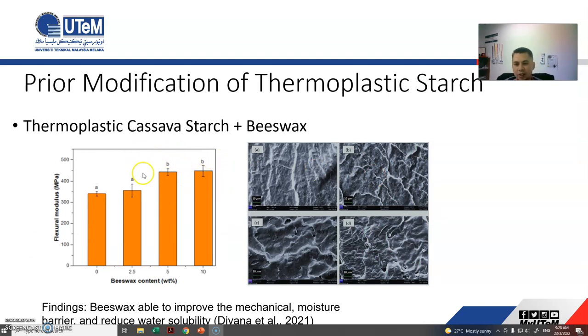In this study, previously we modified the thermoplastic cassava starch by using Beeswax. You can see here that the Beeswax is able to improve the stiffness of the thermoplastic starch, and there is no big impact on the structure of the materials. So Beeswax is able to improve the mechanical properties and the moisture barrier, and also reduce the water solubility, which means increasing the integrity of the materials.